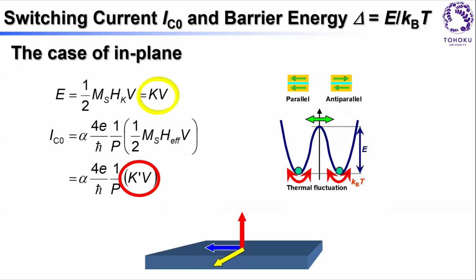But the thing is a bit different when you do an experiment, because you usually do it on thin films, and with thin films, there's a little twist here. The two energies that I have just shown are different because the magnetization has to precess. This easy axis is either left or right, and it has to precess. So the yellow direction is the direction that protects your bit from thermal fluctuation, but the much higher energy barrier, red, is something that you need to overcome by precessional motion. And usually the ratio of yellow to red is 10 or 100. So the in-plane configuration is inefficient. You have to invest more current to switch the whole structure.